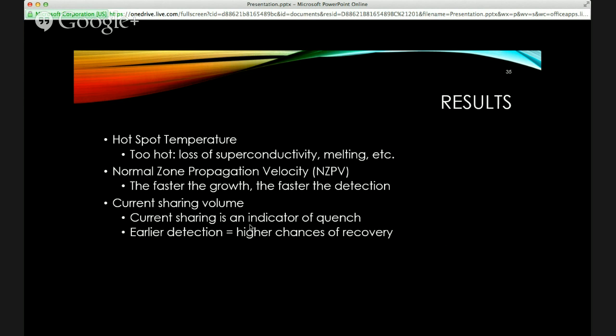So from there, the normal zone propagation velocity, or the NZPV, looks at how fast that normal zone grows. We want faster growth because that means faster detection. When you're comparing low-temperature superconductors with high temperature, the low-temperature NZPV is about two orders higher than what you see for HTS. So you want faster growth so we can detect it faster.